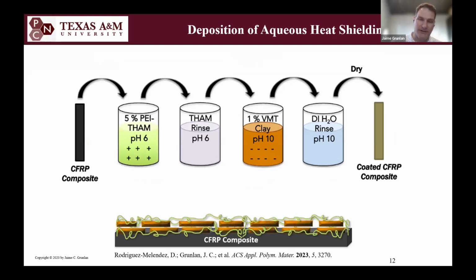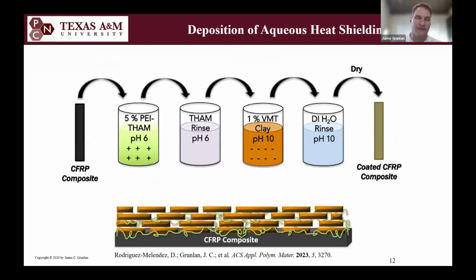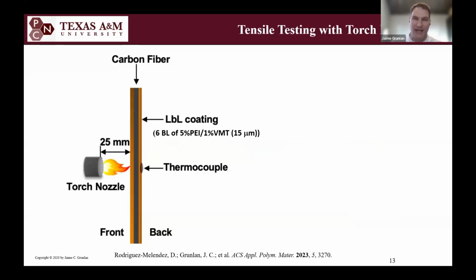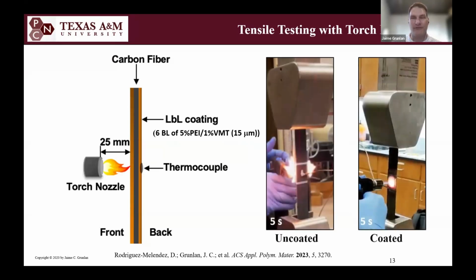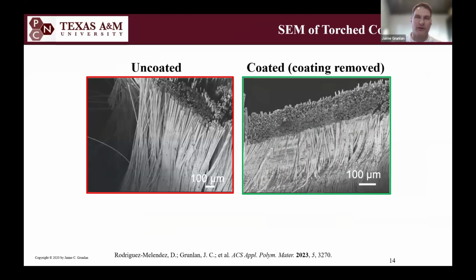In this case, now I'm depositing that nano brick wall onto a carbon fiber reinforced composite, like an aircraft kind of composite that they're making Boeing aircraft with, for example. So this is just a model epoxy, carbon fiber filled epoxy composite system. And so what we did was we actually had a torch on a dog bone of this carbon fiber composite, and then we were measuring a stress strain curve in tension while we had that flame on the composite.